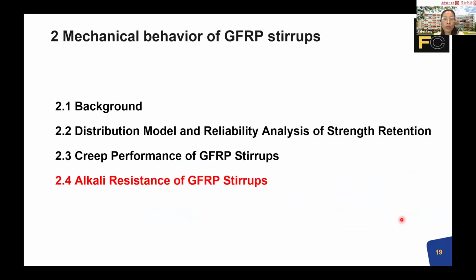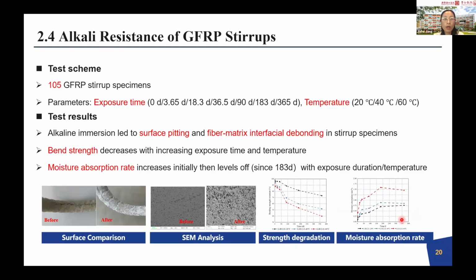And for the alkali resistance, which is also important for GFRP stirrups, we did the durability test, and we put them in the alkali environment in water, with different exposure times. The longest time is 1 year, and also different temperatures. The test method is the same as that used for the FRP longitudinal bars. So we can find that the increase of exposure time and temperature will increase the reduction of the strength. Here is the bend strength, and we find that the tendency varies with time.